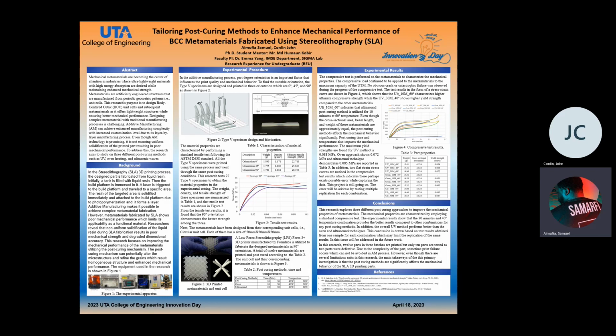This project is still going on. The errors will be addressed by testing multiple replications of each combination. In conclusion, this research explores three different post-curing approaches to improve the mechanical properties of metamaterials. The mechanical properties are characterized by employing a standard compressive test. The experimental results show that the 30 minutes at 40 degrees temperature combination provides better results compared to other combinations.